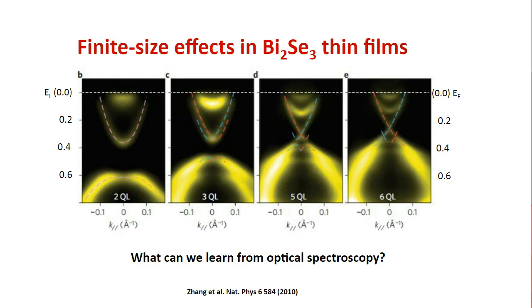A lot of the data out there is really ARPES measurements, looking at the surface states. When we looked into this problem, our optical spectrometer is really sensitive to the bulk states. It's not necessarily sensitive to the surface states directly, because the surface states are hard to observe through a direct optical spectroscopy measurement, but the bulk states are easy to observe.